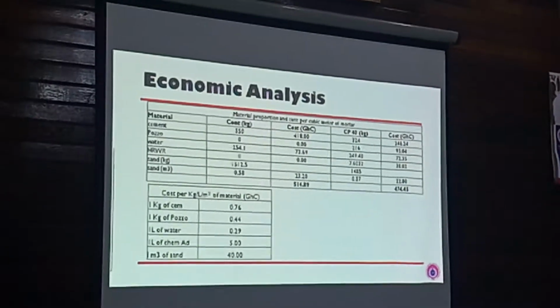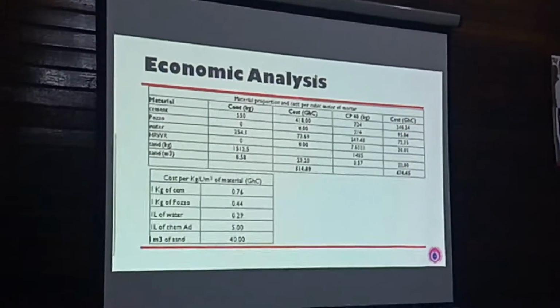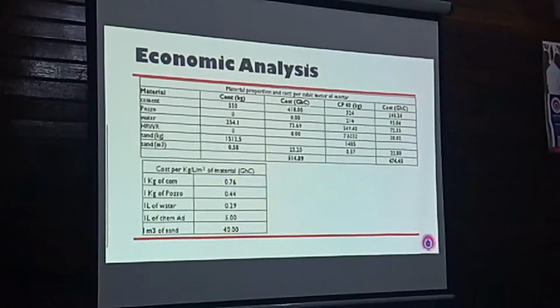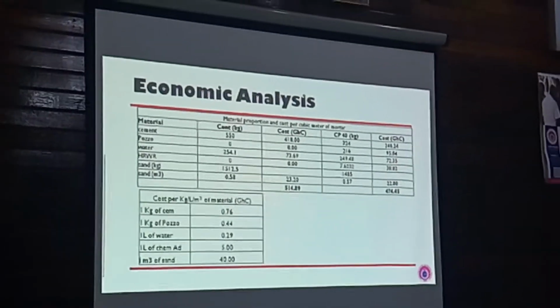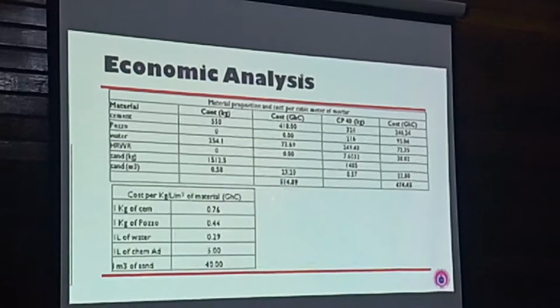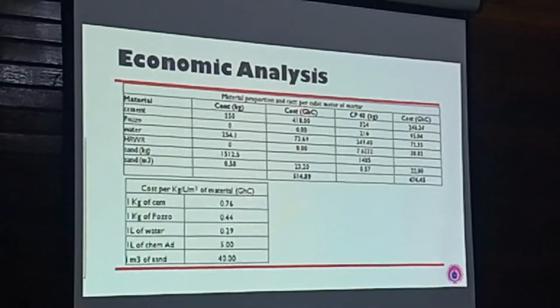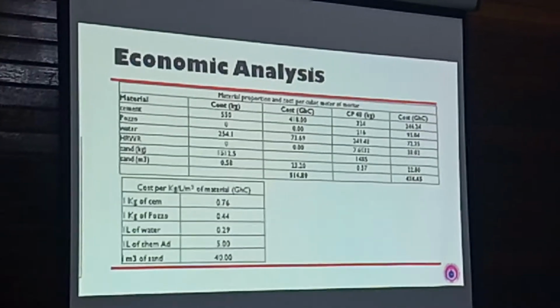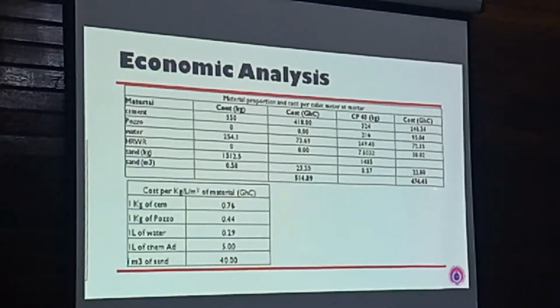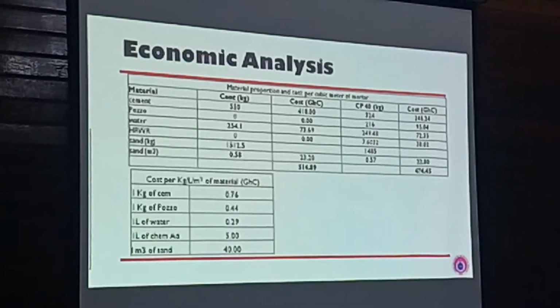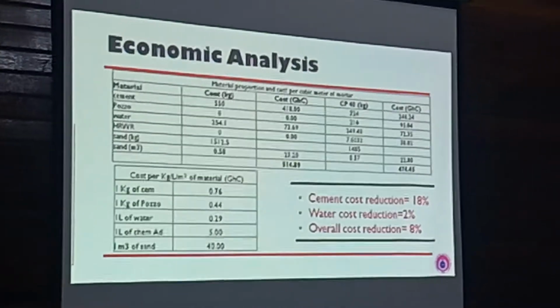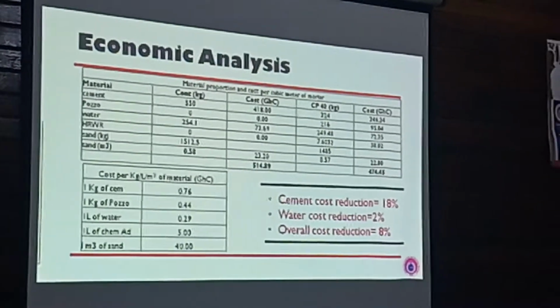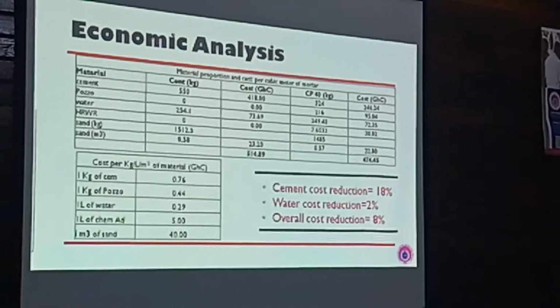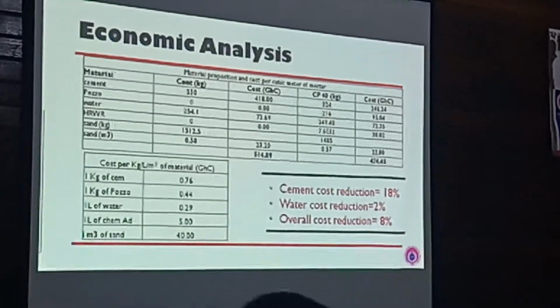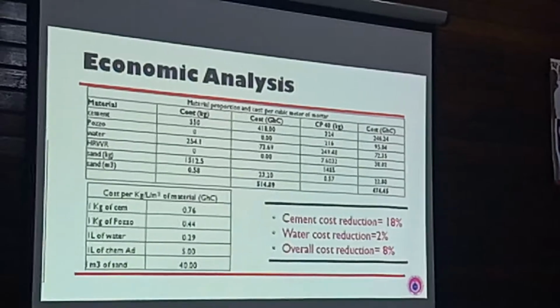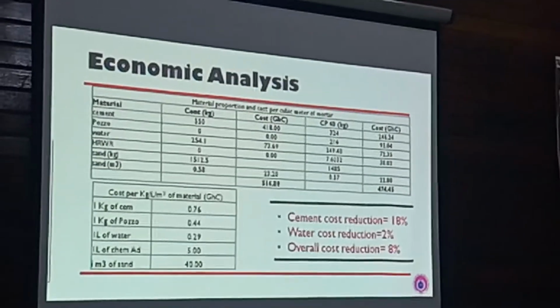So when I compute these things, this is the control cost, which is giving me 514.89 Ghana cedis per meter cube, as compared to 474.45 per meter cube of CP40. So now what do we see? Cement reduction was about 18% when I applied 40% of pozzolan. So water cost too was reduced by 2%.